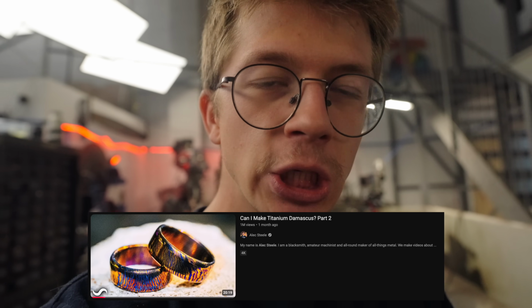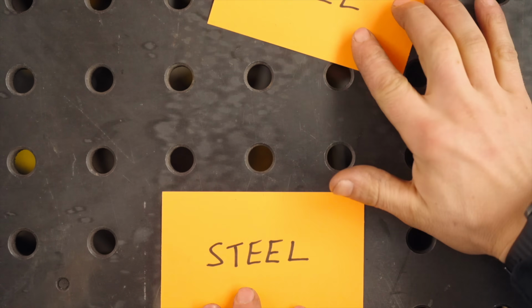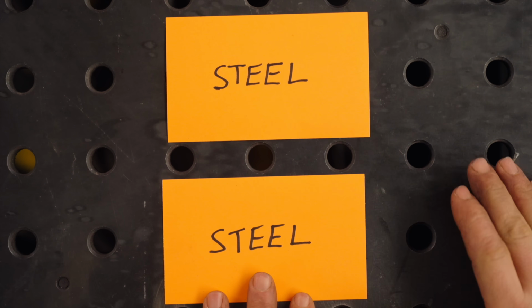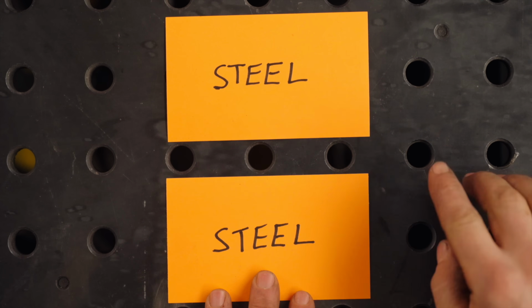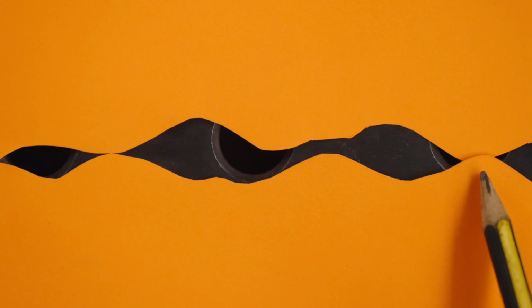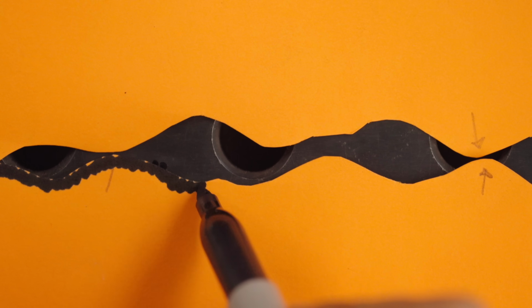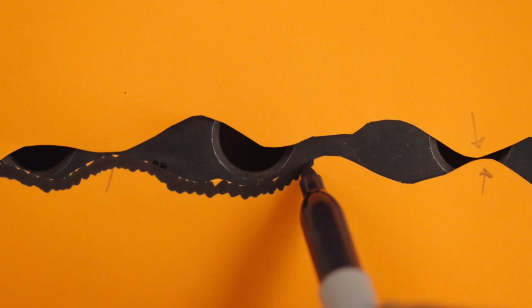As I explained in part 2 of trying to make titanium Damascus, after 15 years of forge welding steel in a blacksmith workshop, I've finally discovered the scientific name for the process and worked out a little bit of what's happening at an atomic level. So we've got 2 pieces of, say, steel that we want to join together. Though they may look flat, in fact, when we zoom in, they're not. Even if you think you've got a great surface finish, close enough, they are only touching at what are called the asperities, the high points. And what's more, there's a nasty old oxide layer, which means the atoms of the actual material aren't touching, which is what you need for them to diffuse across the joint interface.